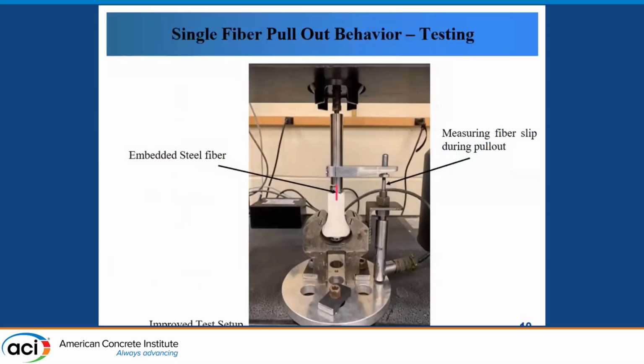This is the improved single fiber pull-out test setup for the investigation of fiber efficiency. You can see there is a red vertical line to illustrate the embedded fiber. A load cell measures the pull-out load while an LVDT on the right side measures the fiber slip. This setup has successfully been tested and more tests will follow in future to characterize the bond between fiber and UHPC matrix.